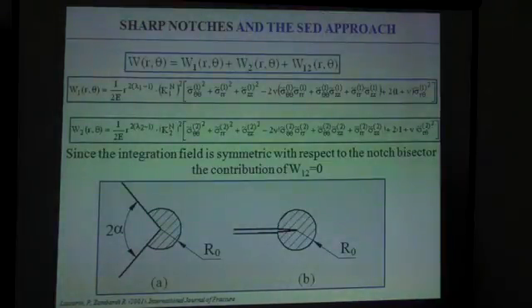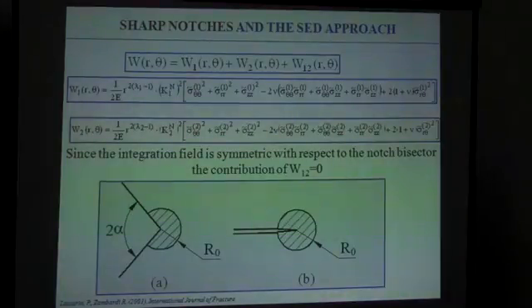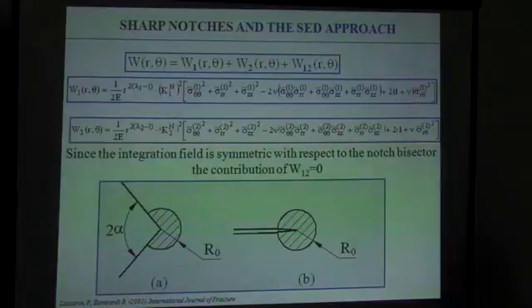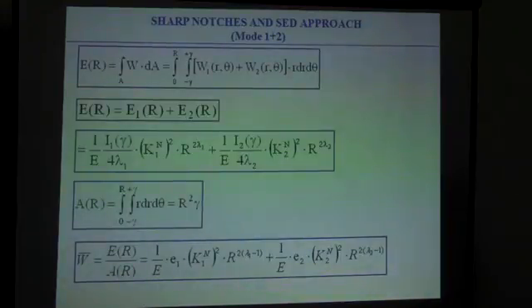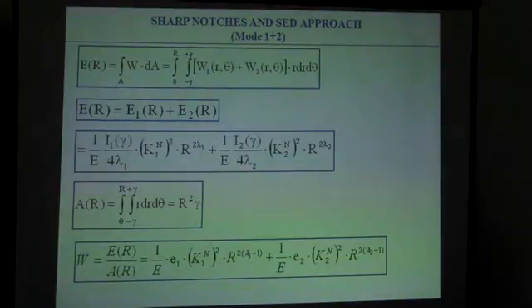Dealing with the strain energy density, our criterion is based on the definition of a control volume around the notch tip or shaft crack, and what we do is to average the strain energy density inside the volume, considering all the components. After simple calculation, we arrive at the last equation reported in the slide, where we can express the strain energy